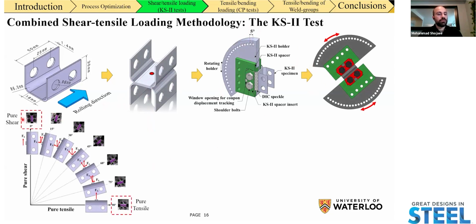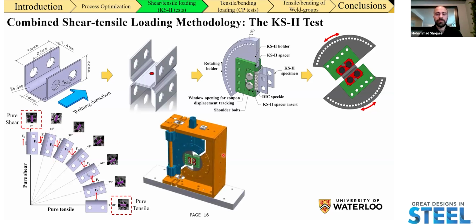We performed our test starting from 0-degree loading orientation all the way up to 90, adding to the tensile component of force that is being applied to the spot weld. We performed our tests in 8 different loading orientations. We also performed it at 10 degrees, which is not shown in this schematic for clarity. You can see the assembled CAD design of the whole fixture.